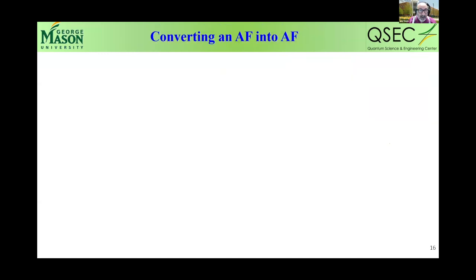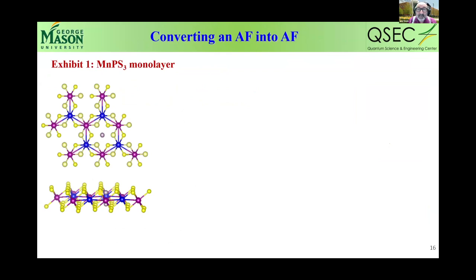Now, the next part is using this understanding of how symmetry makes or does not make a material altermagnetic. Let's think whether we can actually take an existing antiferromagnetic material and, oh, sorry, that's a typo, convert it into an altermagnet, not AF to AF. This would be too simple. So yeah, this is a very known crystallographic motif. There are numerous materials with this. They're all van der Waals exfoliable. So this is one example, manganese PS3.